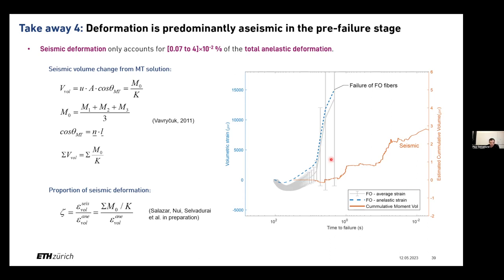And what we've done here is we look at time to failure, and we can take our moment tensor solutions and actually infer the volumetric change from each event, and then correlate that from the material properties. So we go through the math here from the moment tensor solution, the fault plane solution, and then figure out exactly what the volume change was. And then we can look at the volumetric change measured on the fiber optic sensors up to failure. And our sensors were severed here, and the acoustic emissions measure longer.